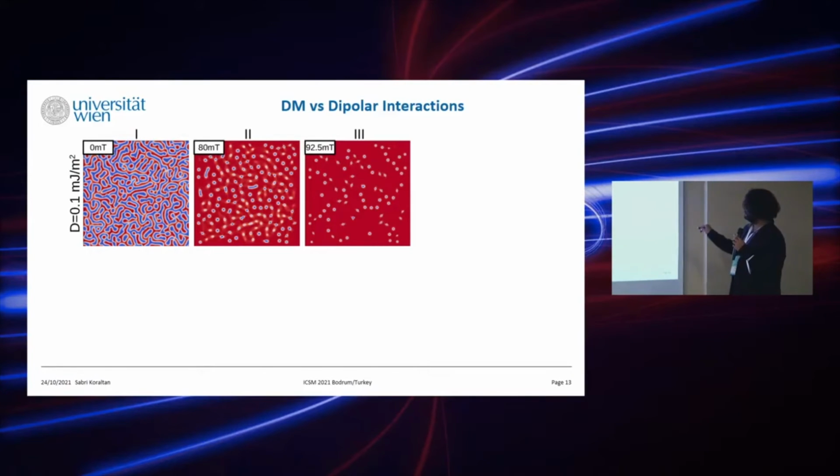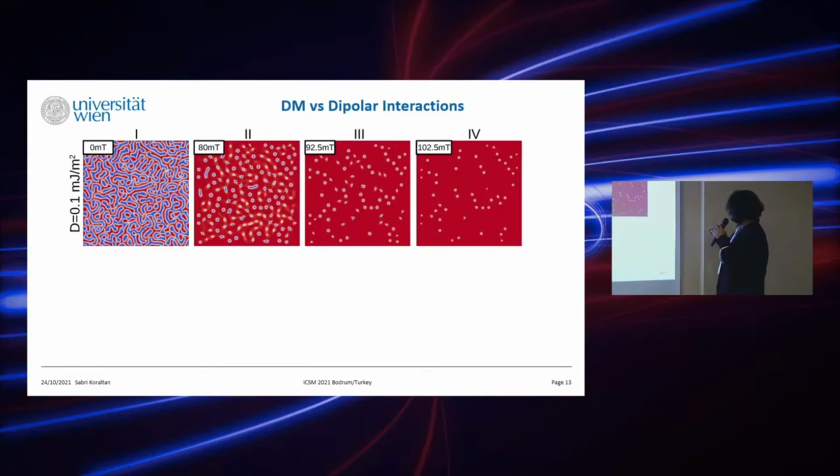We increase the magnetic field further. Then the trivial bubbles are not stable anymore. We only have skyrmions and anti-skyrmions, and then we increase the field further, and we end up only with skyrmions. And we repeat now without DMI. We want to see if the stability that we had in this small structure was maybe a finite-size effect. We didn't apply any periodic boundary conditions. Maybe it was stable because we put it there as a rough parameterization, and it just stayed there.